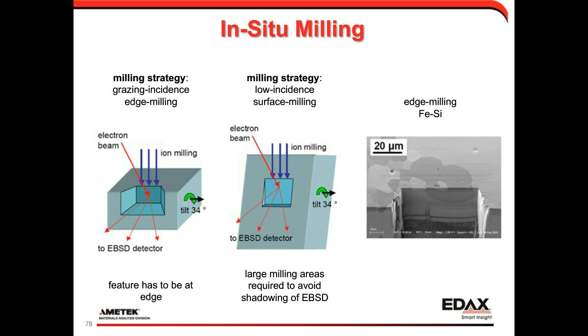We can also go onto the top section of a surface where we do something called a low incidence surface milling, where we come in at near grazing angle to a sample surface, and that allows us to look at an area, and again, we have to make sure we avoid shadowing.